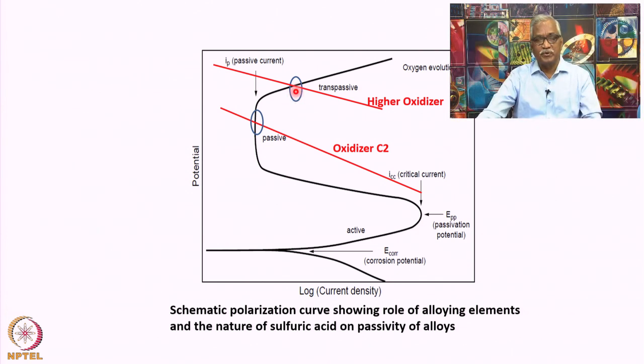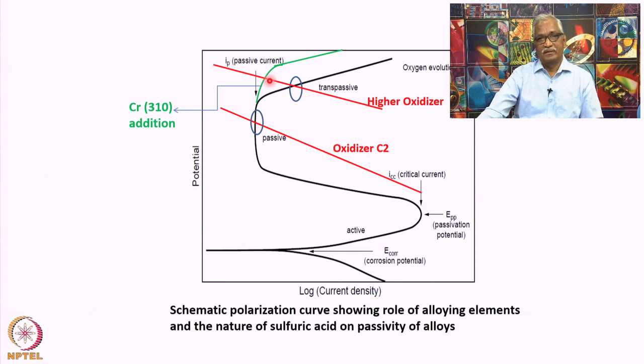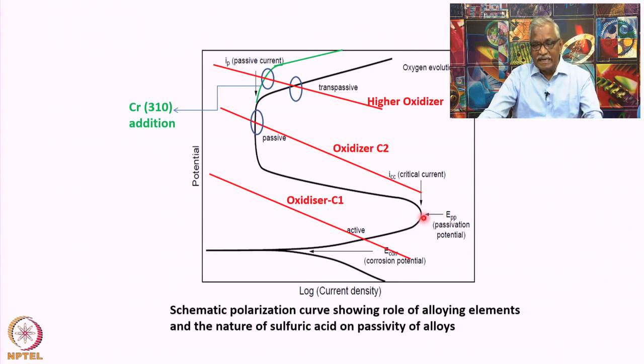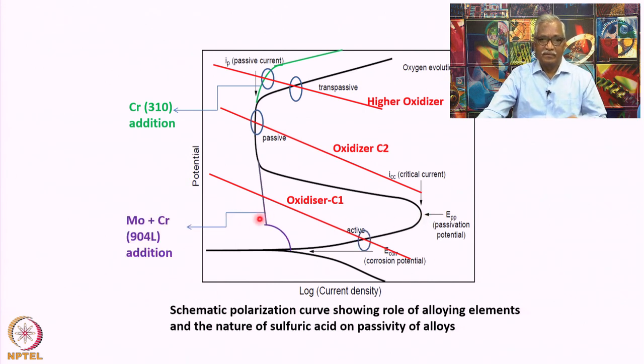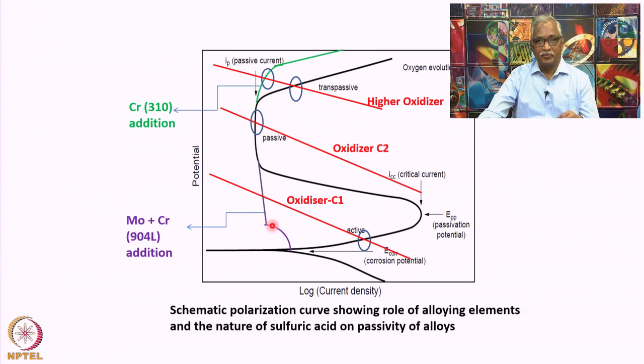To reduce the corrosion rate, we need alloys showing extended passivity. This is achieved by using alloying elements such as chromium — for example, alloy 310 shows very high resistance over a range of sulfuric acid concentrations. When the oxidizer concentration is very small, we need to suppress the critical current density, which is done by adding molybdenum and chromium. By lowering the critical current density, it is possible to reduce the corrosion rate. Alloy selection is thus one means of reducing corrosion in a typical sulfuric acid plant.